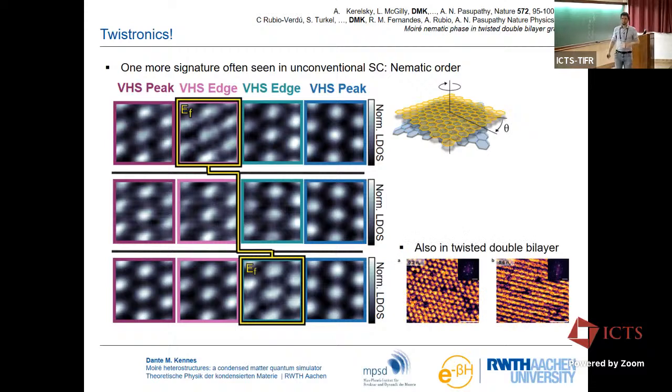And we want to now go beyond twisted bilayer graphene, and this will be in the spirit of the rest of this talk. Now we want to look at twisted double bilayer graphene. So you take a bilayer of graphene in its natural Bernal stacking, another bilayer, you put those two on top, and you start to twist. Additionally, you apply an electric field perpendicular to the stack, and that will open gaps in the bilayer graphene. We've also seen this in the prior talk in this workshop.